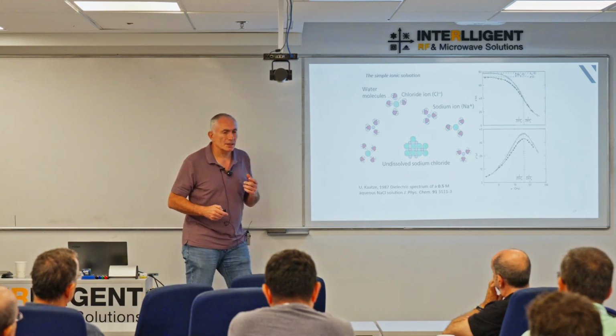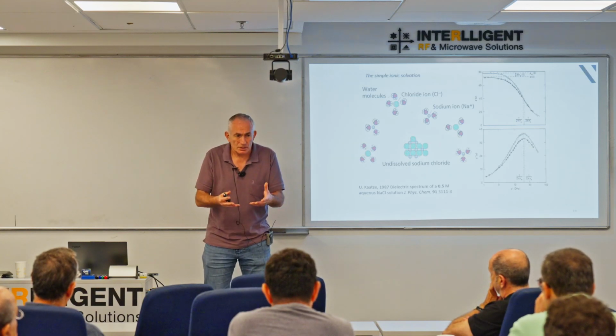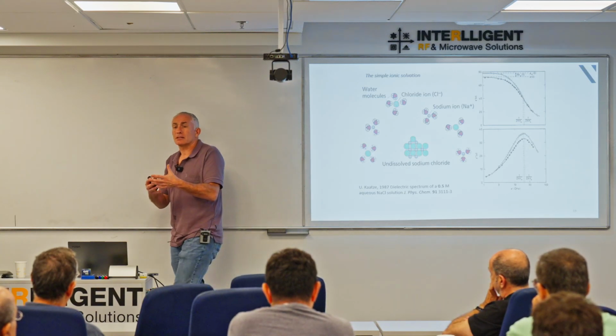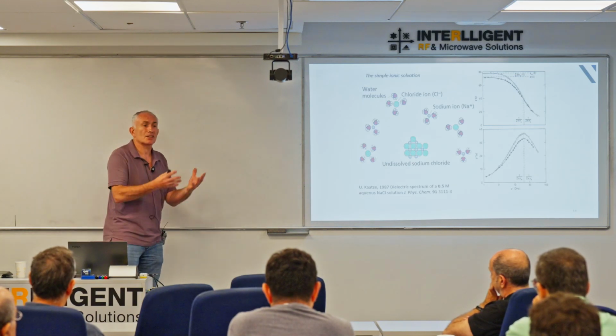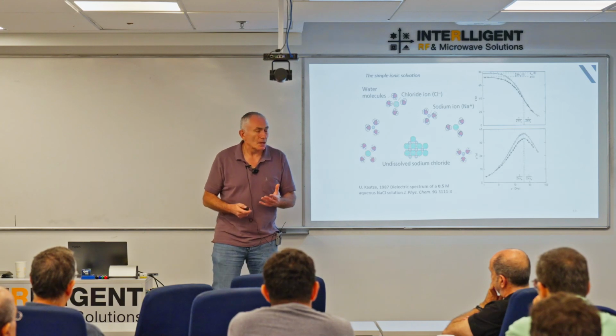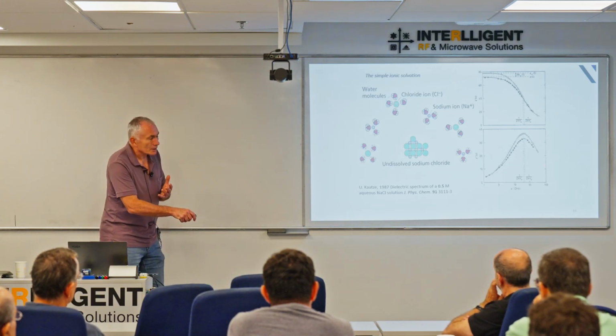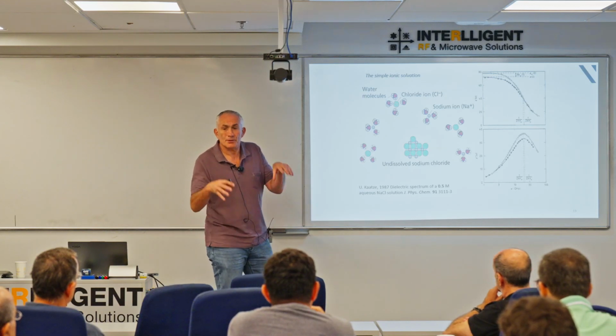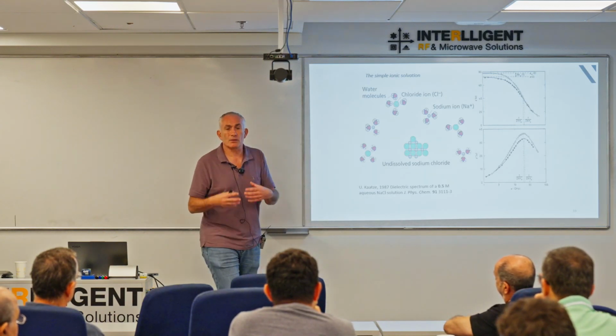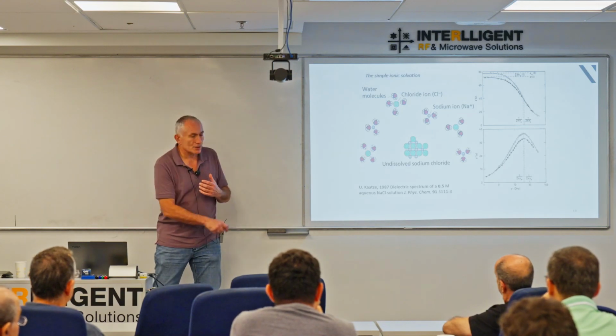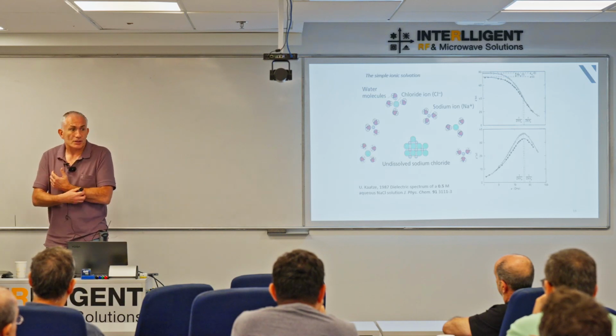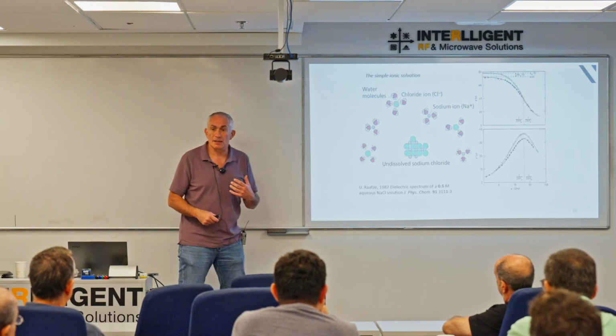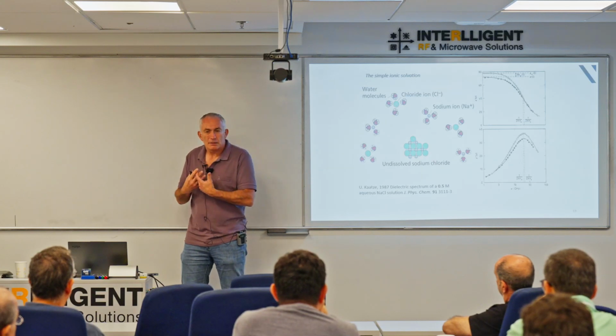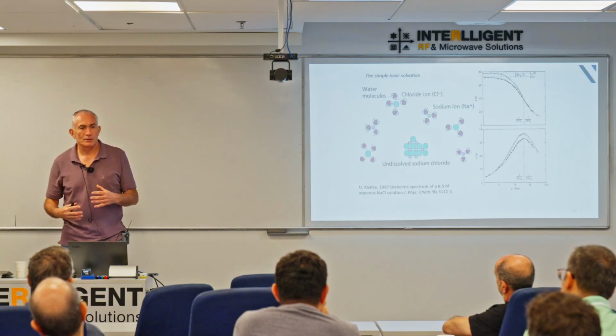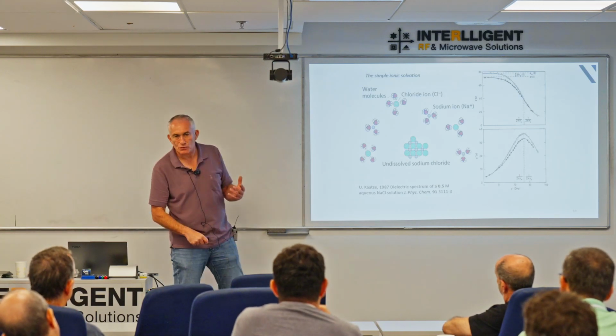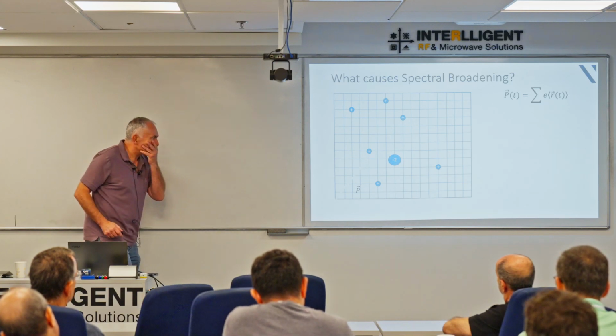Now, what that does to water, it means that water, when it dielectrically relaxes, does it in a cooperative fashion, as a group, a cluster. Okay? And that accounts for why we see the peak of water. But when I put something inside, and when I put the salt inside, some of that water is attracted and kept around the salt in the form of a hydration shell. Others are simply disturbed by the presence of the ions inside there. And in fact, you could almost say there's less of that cooperative type of motion. And so we see shifts and we see changes in that spectrum. So how can we explain that?